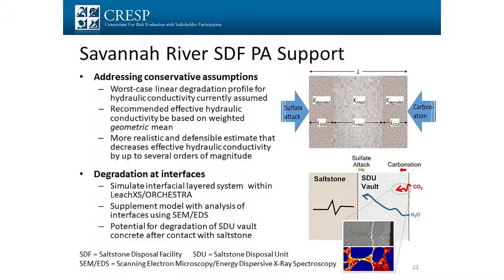And so how do you look at the hydraulic conductivity of the intact versus the degraded material? There was an initial assumption that there are two bounding cases. You either assume flow parallel to it or perpendicular to it. If you go in the literature, and Craig Benson at Virginia helped me look at this, if you do a weighted geometric mean of the two based upon the uncertainty in your hydraulic conductivities, you get a much better representation of the intact versus degraded than you do by looking at either of those bounding conditions. So this is something that I at least hope, at least I've been told, it's going to go into the PA.